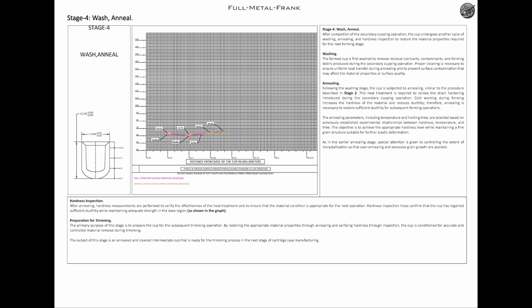Hardness inspection. After annealing, hardness measurements are performed to verify the effectiveness of the heat treatment and to ensure that the material condition is appropriate for the next operation. Hardness inspection helps confirm that the cup has regained sufficient ductility while maintaining adequate strength in the base region, as shown in the graph. Preparation for trimming.